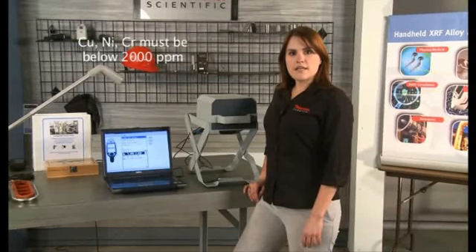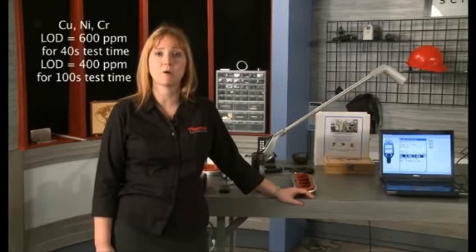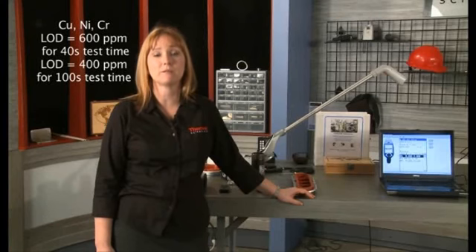The Niton XL3T gold instrument can perform an in-situ analysis of 3 key residual elements found in carbon steels: copper, nickel, and chrome. It has been determined that a combined concentration of 2,000 ppm or greater of these 3 residual elements will reduce the flow-accelerated corrosion resistance of the carbon steel. Known as flow-accelerated corrosion, it occurs when the levels of these 3 elements are out of specification, possibly leading to catastrophic failure. Since we have a combined LOD, limit of detection, of 600 ppm for the sum of copper plus nickel plus chrome with our high-performance Niton XL3T gold instrument, it can accurately determine whether total residual elemental content is greater than or less than 2,000 ppm.